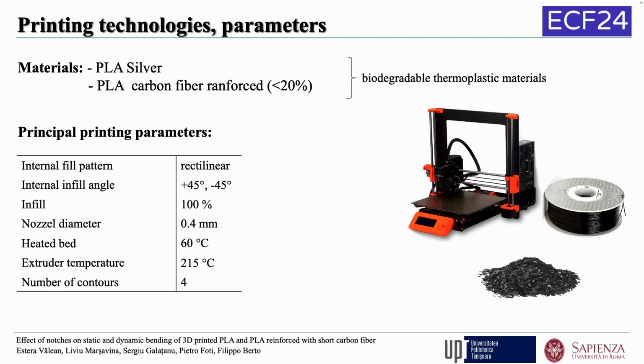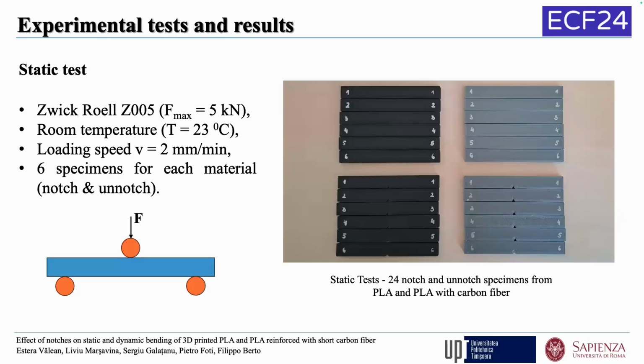So we use a rectilinear pattern, plus minus 45 degrees infill angle, 100% infill, nozzle diameter 0.4. The heated bed was at 60 degrees Celsius, and the extruder temperature 215 Celsius. And we use some contours around the edges of the specimen.